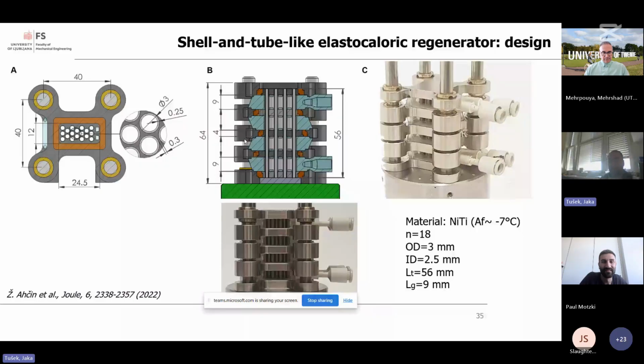Okay, so I'm almost out of time, I guess, but let me just briefly present our elastocaloric regenerator. It's a so-called shell and tube regenerator made of nickel-titanium tubes, which are shown here, and those tubes are supported with support elements along the length, which prevents buckling of the tubes, but at the same time guides a heat transfer fluid in a cross flow around the tubes. Here is the video which shows the operation from the initial state up to steady state conditions in a heat pumping mode.